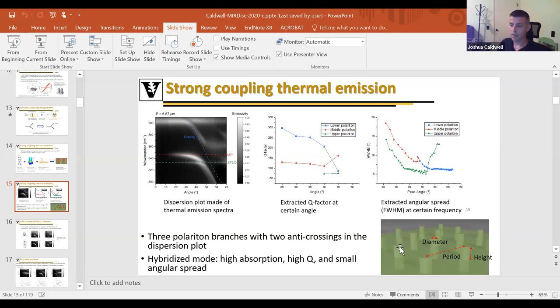And so the key outcome of using this monopole mode is that the individual pillars, provided they're spaced within the distance of the propagation of that polariton, will start to couple together and interact, leading to a collective monopole resonance.